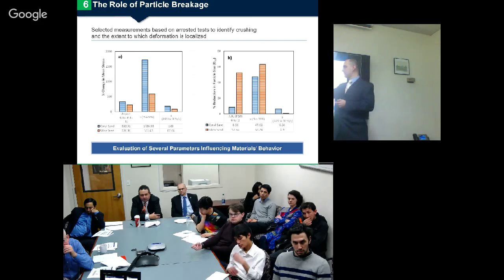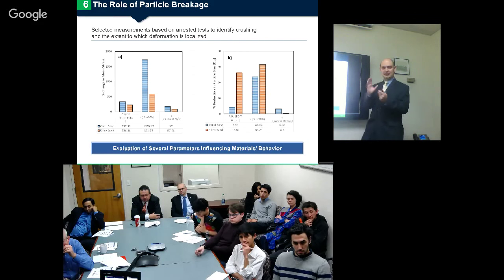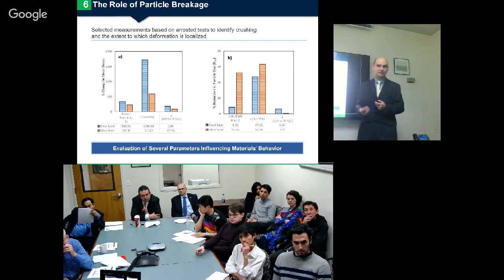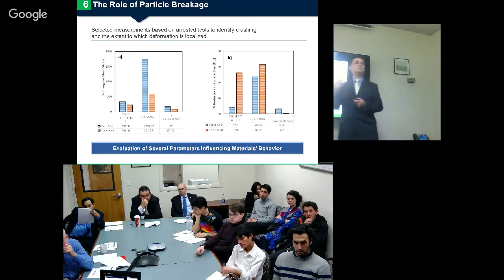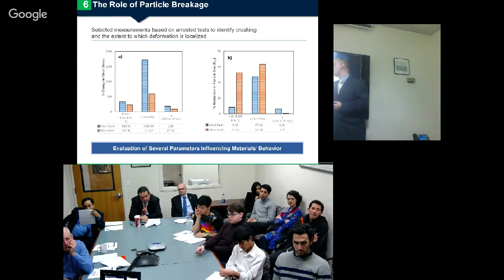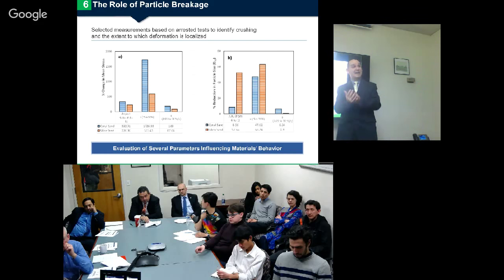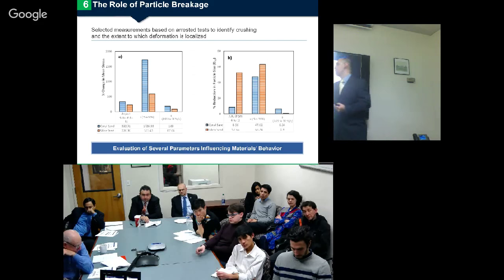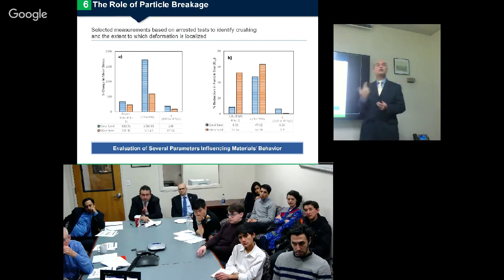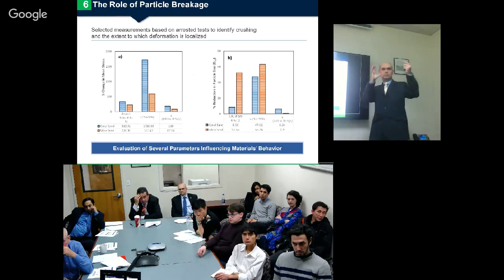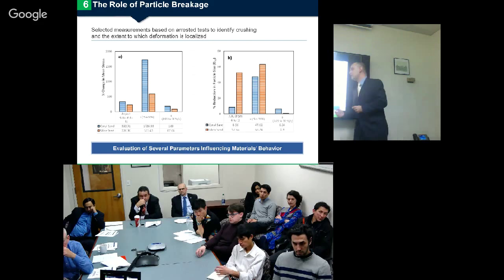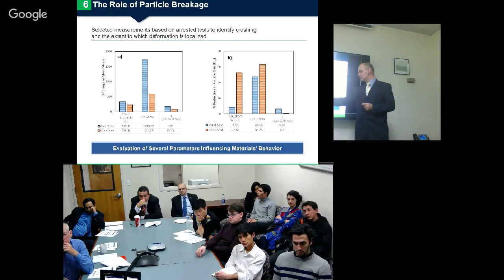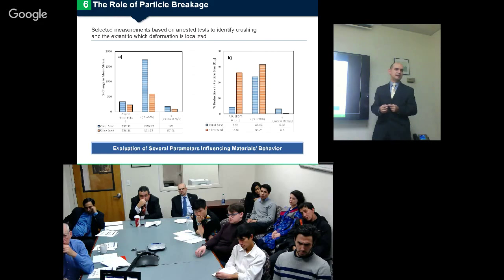So from this left figure, we can see obviously that the axial deformation, the porosity, is influencing the change in the mean stress more than the strain rate. So I was expecting to see something like this, a change of the stress-strain behavior, also the stiffness of the material, but not that much. Aspect ratio is also important, but this too. Plus here, the reduction of particle size, how the particle moves from the original size to smaller sizes, is mainly governed by the aspect ratio and the porosity or void ratio of the material. Whereas for the strain rate, there is no